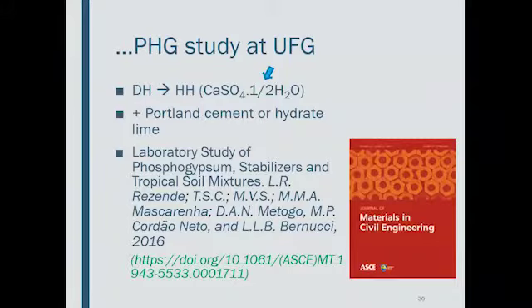Then, in the next phase of this study, we thought about transforming the dihydrated phosphogypsum by a thermal treatment into the hemihydrated type, trying to solve this problem about the swelling. And then we also added cement and lime, trying to improve the mechanical behavior. The main results of this work are presented in this paper, and I will summarize them briefly in the next slides.